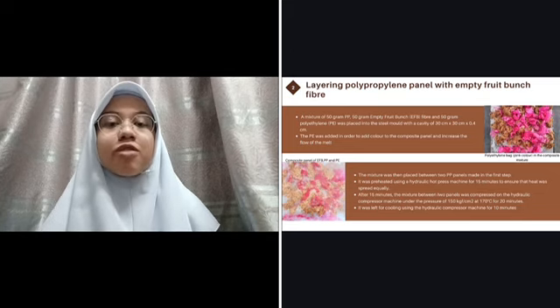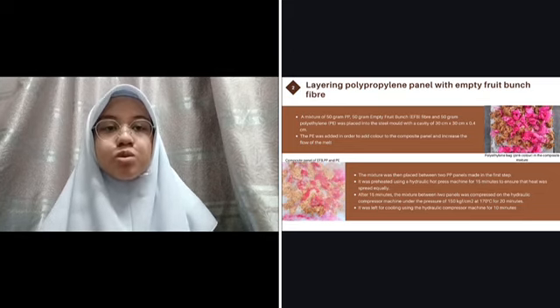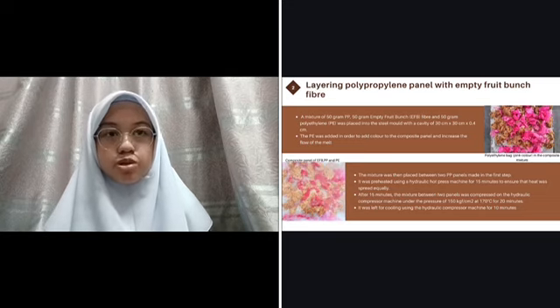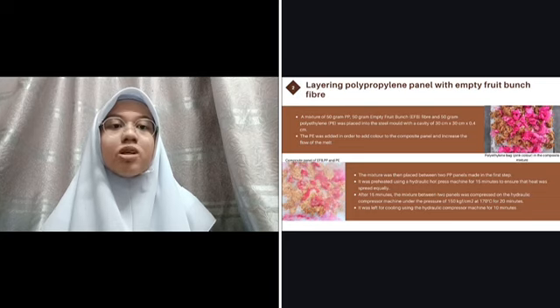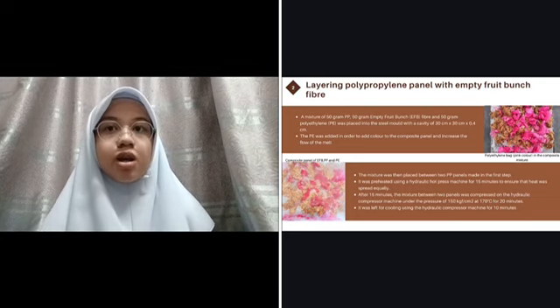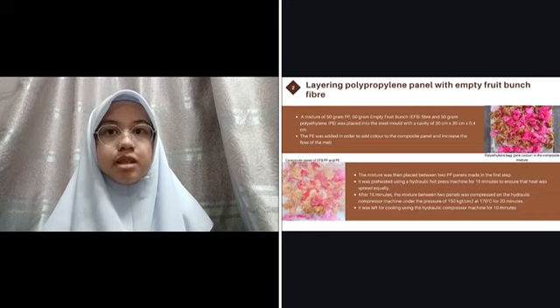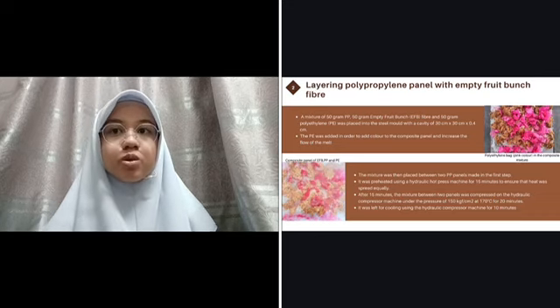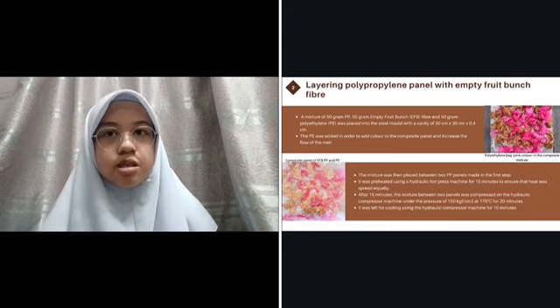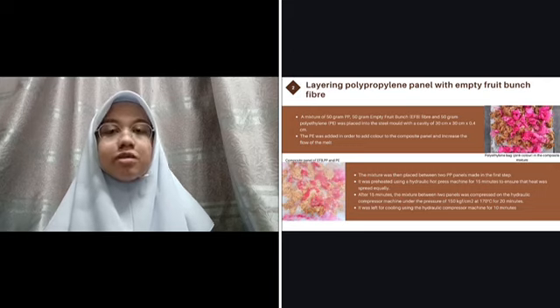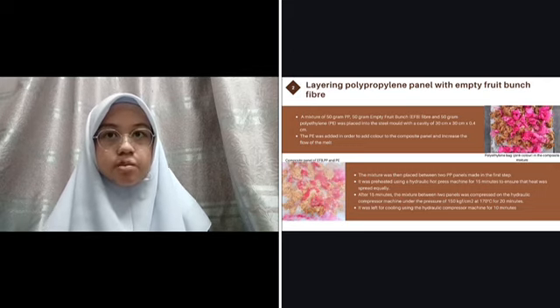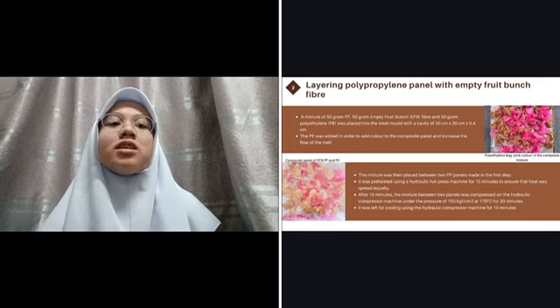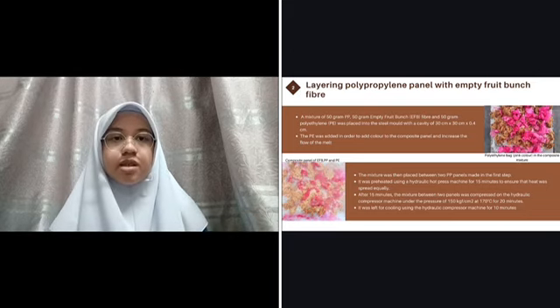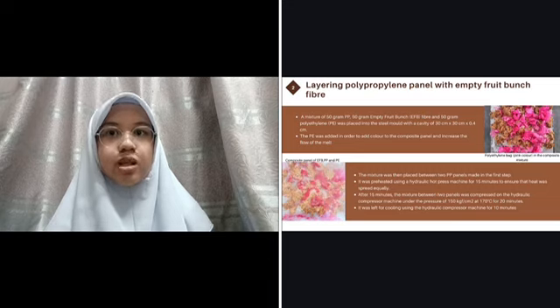So the mixture of the said materials, 50 grams of polyethylene, 50 grams of polypropylene pellet, and 50 grams of empty fruit bunch fiber, was placed between 2 polypropylene panels that were produced in the first step. It was preheated using a hydraulic hot compressor machine for about 15 minutes to ensure that all the heat was spread equally. After 15 minutes, the mixture was compressed again using the same machine under the pressure of 150 kg force per square centimeter at 170 degrees Celsius for 20 minutes. And lastly, it was left for cooling using the hydraulic compressor machine for 15 minutes.